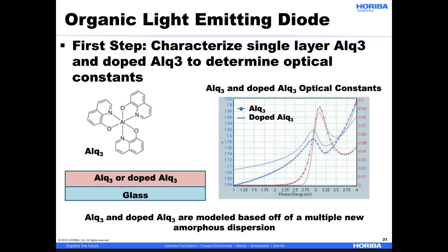So what we're looking at here is the structure of ALQ3. This can be a very basic sample of ALQ3 or doped ALQ3 just on glass, so a very basic one-layer sample. You can see the difference in the optical constants for the actual ALQ3, shown as dots, and the doped ALQ3 shown as a line. As we dope ALQ3, we change the optical properties of the ALQ3 itself. So it's important to know these optical properties and what's actually happening with the ALQ3.